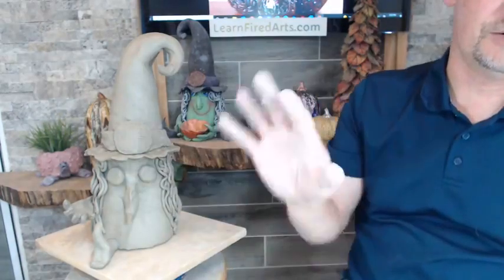If your kilns are out in your garage, or they're out in a shed, somewhere that isn't heated and air conditioned and controlled temperature, they can collect humidity. So some of my kilns are in a room that's not heated and air conditioned, and it's kind of exposed to the outside. And if I put those pieces on top of the kiln and I heat them and they dry, and then I let them set for a few more days and it gets real damp and humid, that clay is going to take on moisture again. And so the piece won't be completely dry. So that's why I say fire it shortly after you get it completely dry sitting on top of the kiln. Fire it to the temperature for the clay body you're working with, whether you're working with low fire or mid-range clay, you're probably going to do like an 04 firing.